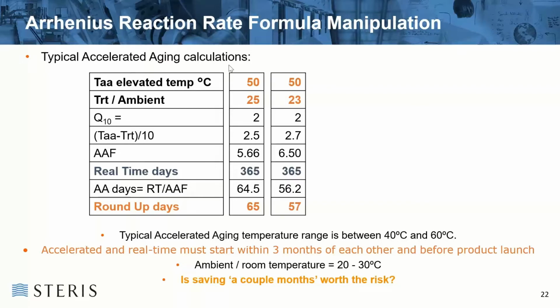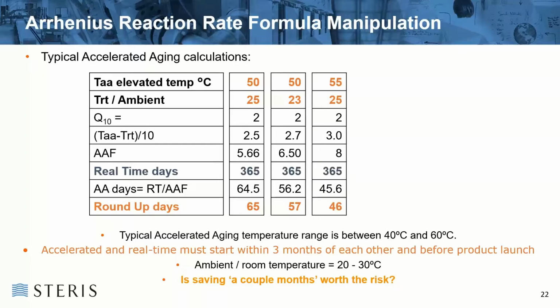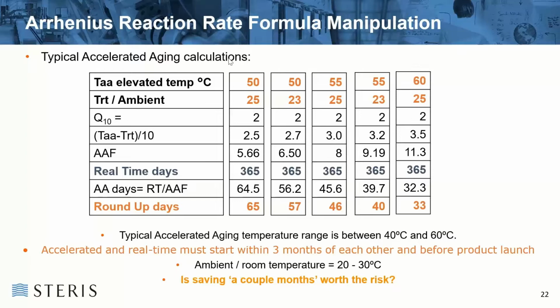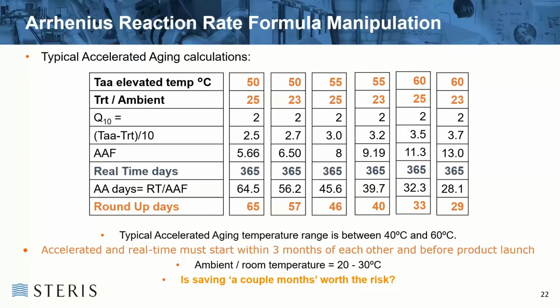However, if we manipulate that formula and just change the ambient rate by 2 degrees, again with all the other figures staying the same, we're now down to 57 days. Again, another saving in the whole study. If we increase the accelerated aging temperature to 55 degrees with an ambient of 25, all of a sudden we're down to 46 days. And that keeps going on and on, the more you play with the figures. Up as far as 60 degrees, which is the highest recommended within the standard, because the calculation becomes non-linear after that. So the last one there is 60 degrees with a 23 degree ambient, and you are achieving a full year in 29 days.